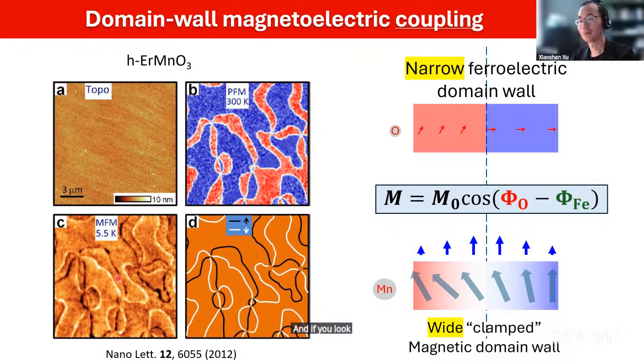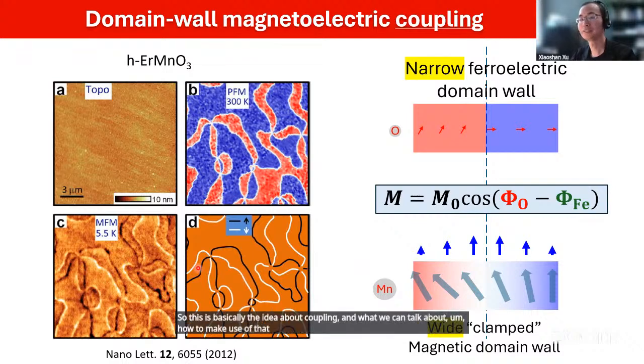And if you look at the magnetic property, oh, it's quite interesting. The signal, the white means high and the black means low, is basically concentrated along the domain walls. You can see that, right? And this is a cartoon of this. So that's exactly the idea you see here. If you generate the domain wall, you can immediately make something go from non-magnetic to magnetic along the domain wall, basically given by these lines. So this is basically the idea about coupling, and we can talk about how to make use of that in the outlook in a moment.